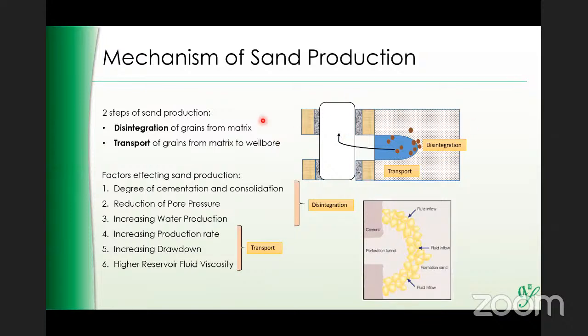So the effective strength of the rock is reduced because you're flowing, you're reducing the pressure, and because of that, the rock becomes weaker, its strength becomes lower, and disintegration takes place. Then increasing water production. So when you see that the water is coming in, you will have water and oil two-phase flow within the reservoir. This changes the capillary pressures, and the capillary pressures which are holding the particles in place become weaker, and the sand gets disintegrated from the matrix.